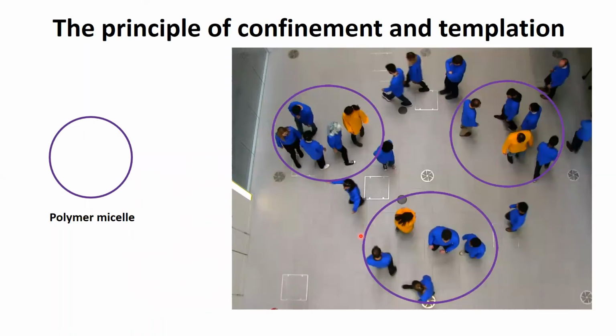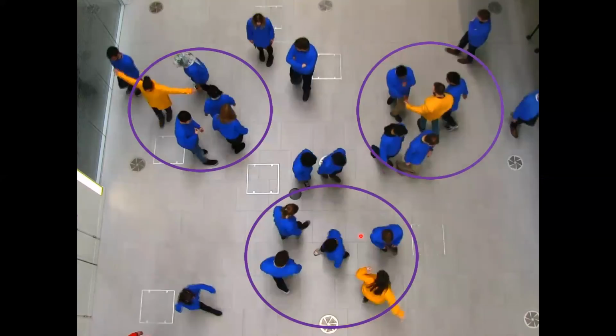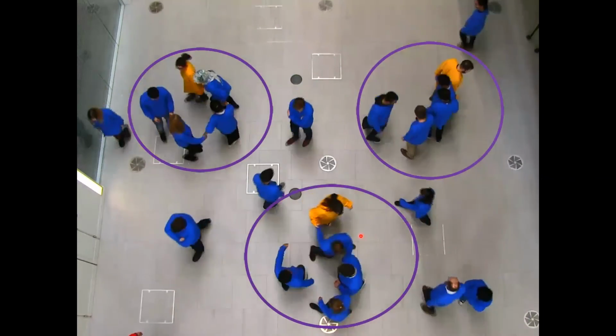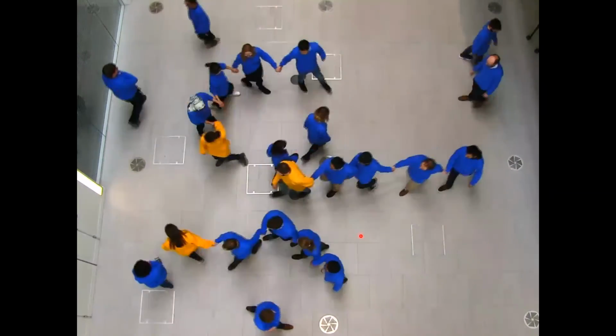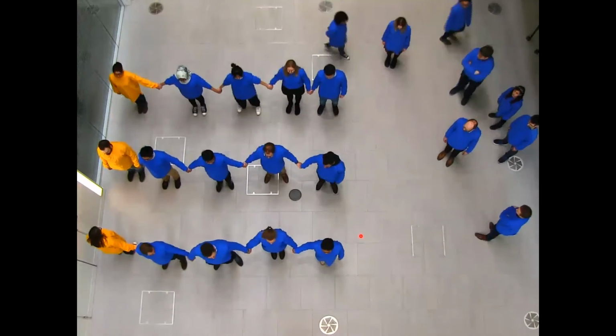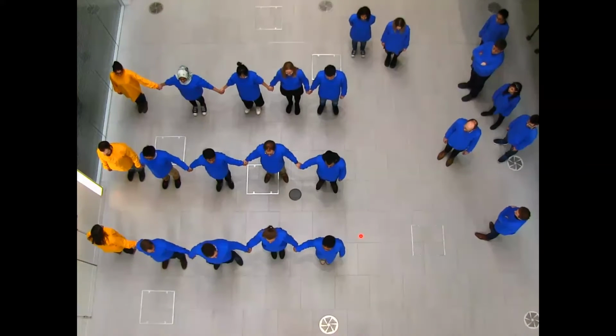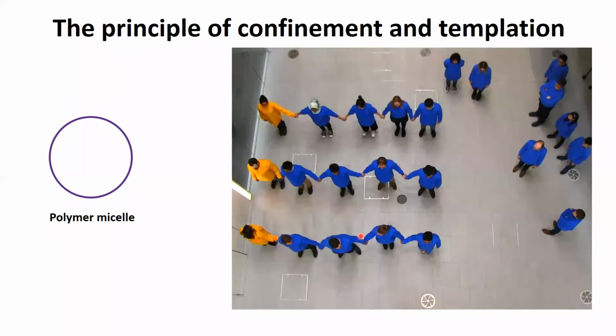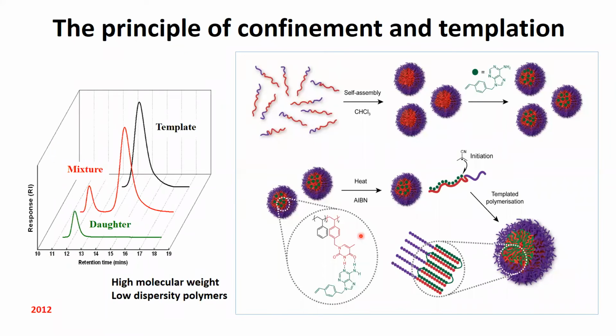A number of years ago, my group became quite interested in whether we could think about confinement and templation from a synthetic perspective to try and improve polymer synthesis. What we did was embed the monomers within polymer micelles, within these little pockets. And there's another video to show that now only monomers within the purple circles, the micelles, were able to react, and all the other monomers were left behind. So rather than using conventional capping, we started to use confinement, being inspired by nature, because that's how they do it. And this works really well, and quite remarkably.